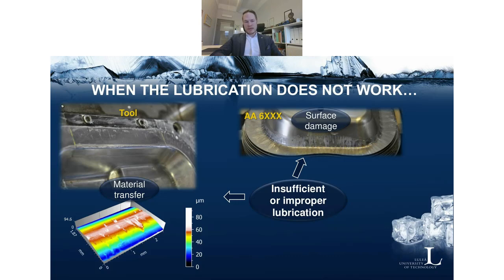component. This is often mirrored also on the tooling, where you have a lot of transfer, and the 3D topography image there in the bottom left shows the radius that we are looking at in the photograph above, where you can see that there are tens of micrometers of transfer after only, I think this is 5 strokes that we have taken this image after. So 5 components with insufficient lubrication. So it's a very fast development when things go wrong, and it requires a lot of effort to reset the system to its intended state and performance.